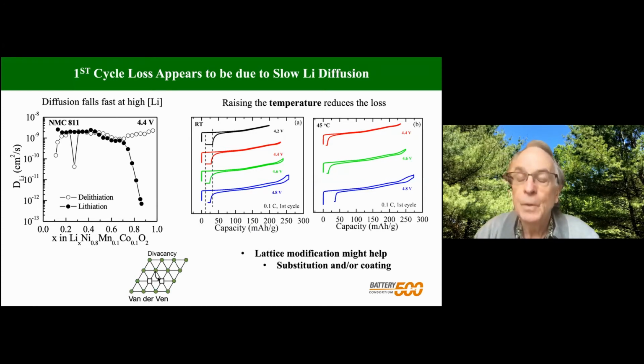If we go to 4.6 volts, you can see that we're now getting some increased polarization, so we're getting some damage to the material, more resistance on the surface, and this is preventing us from getting such a reduction in the first cycle loss. And if you go to 4.8 volts, it's even more damaging. So clearly the message here is we shouldn't go above 4.4 volts, and diffusion is again controlling the situation.